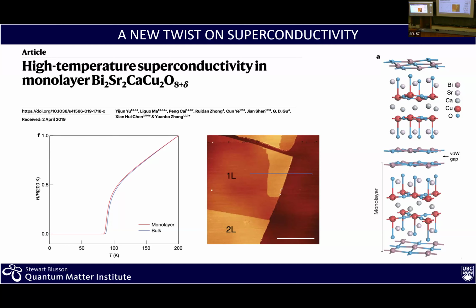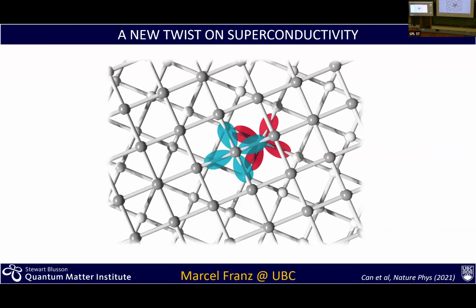Now, if you can do that, then the question naturally arises, could you stack and twist this material versus twisting graphene? What would happen then? There's a question that my colleague Marcel Franz asked. So the idea is very simple. You take 2 of these layers now. Each of them has a d-wave gap, a d-wave pairing symmetry. Now you rotate them by 45 degrees, and you align the nodes of one layer with the direction where the gap is maximum in the layer below. And what would happen then? The question is, well, if there is an interaction, you can now give rise to a completely different kind of superconductor, an even more exotic superconductor.